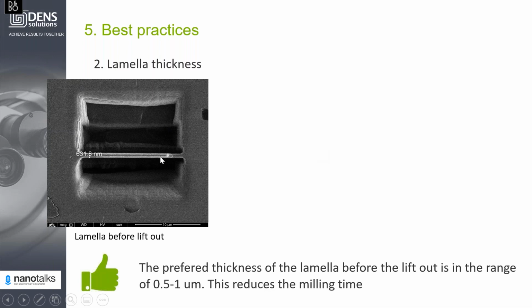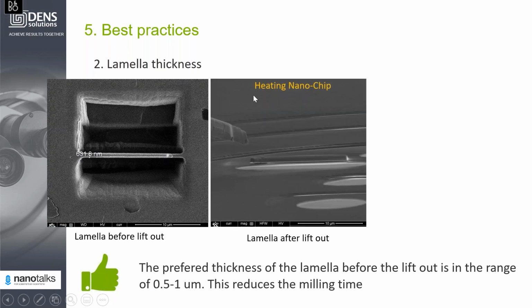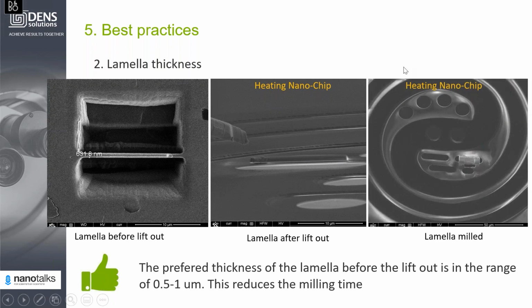Instead, you can reduce the lamella thickness down to 0.5 to 1 micron before the transfer. Here you see the heating chip, this is the manipulator, and this is the lamella transferred, which is pretty small. In this case, the advantage is that you don't need to use very high currents, first of all, and secondly, the process becomes simpler. And this is the heating nanochip, top view, where you already have the prepared lamella, and you barely see any damage to the silicon nitride.